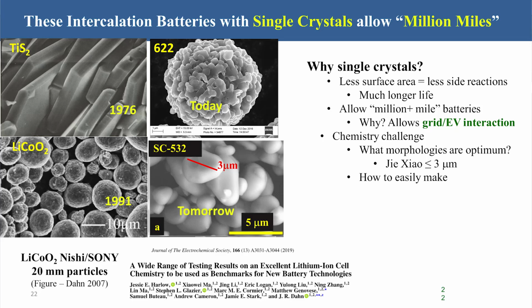So I said, today we use meatballs. We didn't originally use meatballs here at Exxon. We basically did the same thing as with beta alumina. Let's use large single crystals. And we had 3 sizes of single crystals, what we call battery grade, which is a higher surface area, chemistry grade. And then the physicists had the physics grade. The physics ones were like several millimeters long, so they could all put all their tabs on there and measure their physical properties. But these are the ones typically we use for commercial cells.